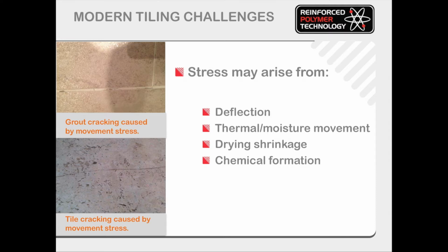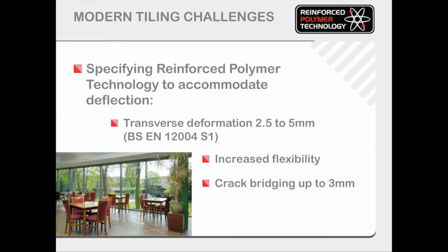Chemical formation. For example, ettringite is formed as a reaction between hydrated Portland cement and calcium aluminate within an anhydrite or calcium sulfate screed. Its crystallized formation can affect the structure of the cement, thus resulting in a weakening or breakdown within any cement-containing adhesive. The substrate must be capable of supporting the tiled weight, and any type of dynamic or static loads and impacts the tiled installation may be subjected to. Floors where deflection is anticipated should be strengthened before the commencement of tiling.